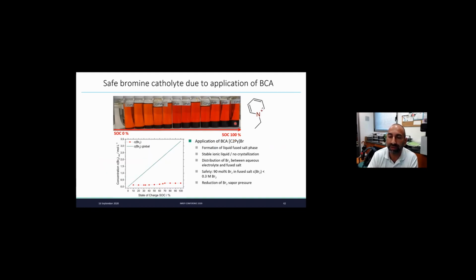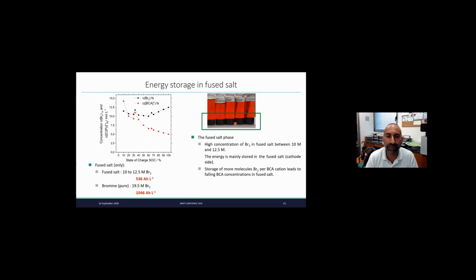So you can see here some images of one of the bromine complexing agents that we use, based on pyridinium. So this is ethyl pyridinium. And based on the states of charge, you can see here that you've got 2 phases, and the second phase is the complex that you form. The good thing about these complexes is that they maintain the very high ionic conductivity of the electrolyte, and also they increase the energy density of your electrolyte. So they are doing really 2 good things for you.